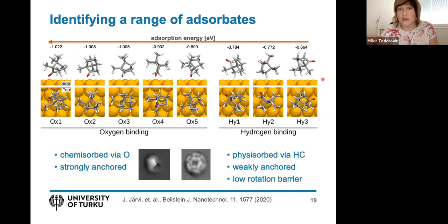And indeed, when we checked the electronic structure of the systems, we found that the covalent bond was forming here on the left, and these molecules were chemisorbed and more strongly anchored to the surface. While the top three were more physisorbed and they could rotate in place very easily. And so when we looked at the AFM image, we thought that this one here that looks like a windmill was this kind of weakly adsorbed molecule that was rotating in place. And you can see the six spokes because of the six-fold symmetry on copper 111. And so these images that didn't move were better candidates for matching the chemisorbed structures.